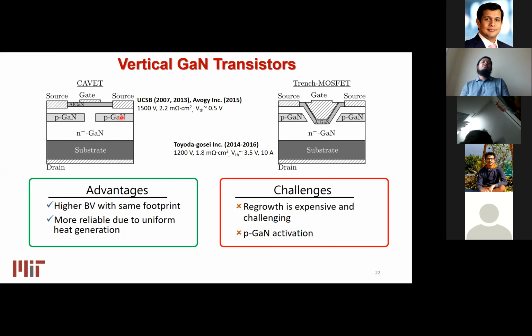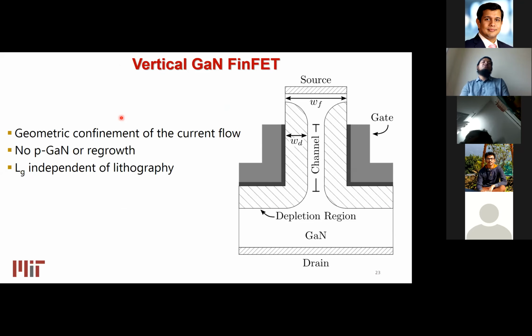Toward this goal, our group a few years ago came up with a unique structure where we don't have these two problems. Again, this is the schematic diagram of the structure we are using. We have drain at the bottom and the source on the top. The way we make these devices, we define a fin-shape geometry in the channel, and we put the gate dielectric and gate on the sidewall of the channel. In this way, we use the gating depletion mechanism between the gate and semiconductor channel to turn on or turn off the device, and the current flows across the sidewall of the device. As we can see, there is no P-type region present in this device, and there is no need for regrowth. That makes these devices very attractive for fabrication and commercialization.